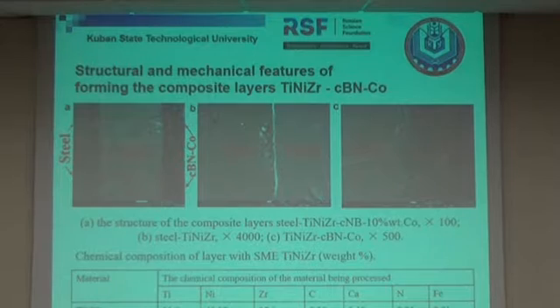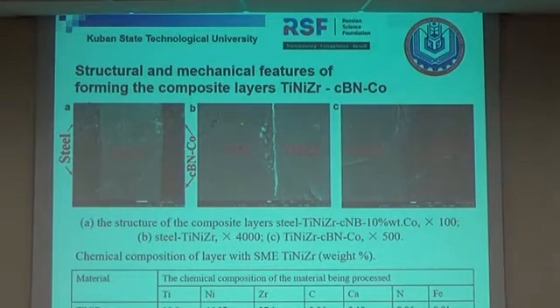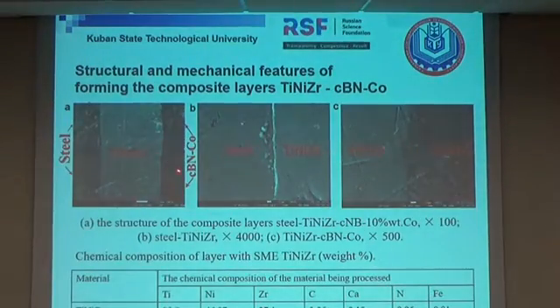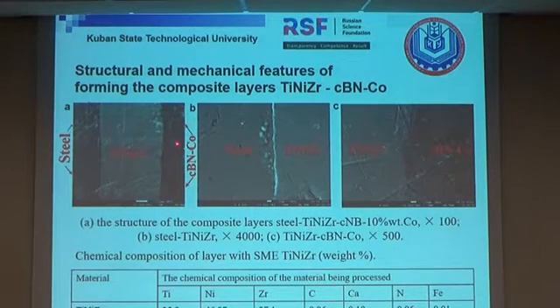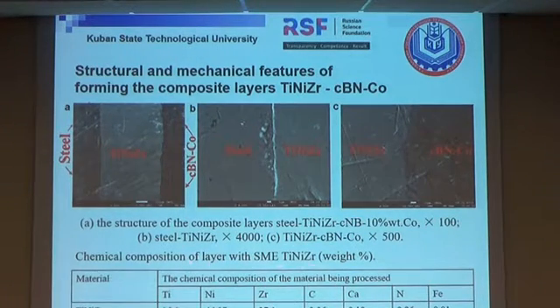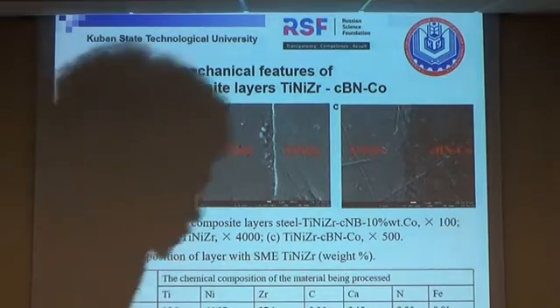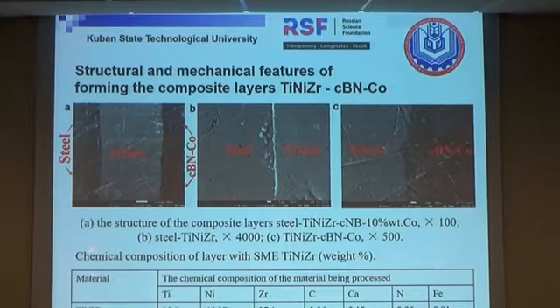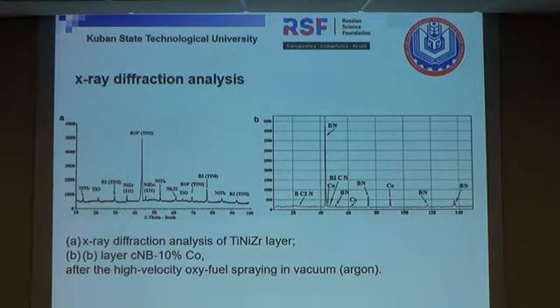In this picture, we can see our layers: steel, composite layer titanium zirconium, and composite layer cubic boron nitride with cobalt. The chemical composition of the layer with shape memory effect, titanium nickel zirconium, is in this table. X-ray diffraction analysis is shown here after the high velocity oxyfuel spraying of mechanically activated powder in a protected atmosphere.